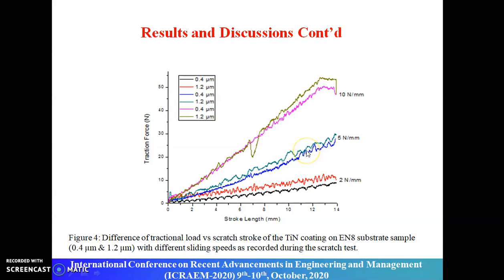The present investigation shows that the bonding strength of the coating increases with the decrease in the substrate surface roughness. The coating adhesion obtained on lower surface roughness, that is 0.4 micrometer, was superior to coating adhesion obtained on higher surface roughness substrate, that is 1.2 micrometer.